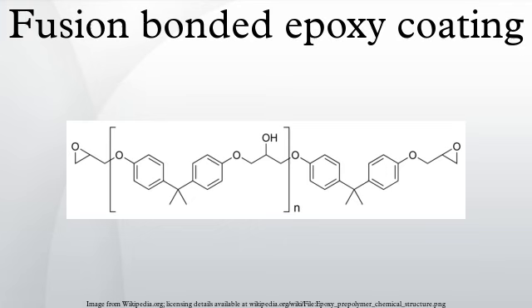The fluidized powder is sprayed onto the hot substrate using suitable spray guns. An electrostatic spray gun incorporates an ionizer electrode on it, which gives the powder particles a positive electric charge. The steel to be coated is grounded through the conveyor. The charged powder particles uniformly wrap around the substrate, and melt into a liquid form. Internal surfaces of pipes are coated using spraying lances, which travel from one end to the other end of the heated pipe at a uniform speed, while the pipe is being rotated in its longitudinal axis.